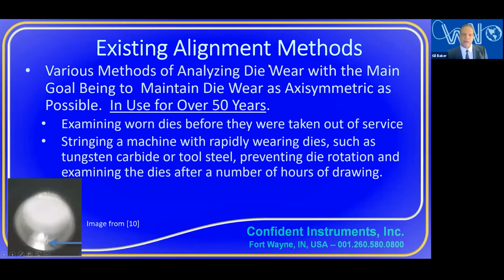Okay. Now, there are existing alignment methods where you're considering the cast as a steady state issue, not something you can just measure in the machine geometry. Most of those methods, for about 50 years, have used the die wear, analyzing the die wear to determine how to optimize alignment, with the goal of maintaining as axisymmetric or symmetric a die wear as possible. So this involves examining the dies. Now, one method is just looking at worn dies. Maybe you've used the dies long enough, you want to replace them. Just look at the worn dies.